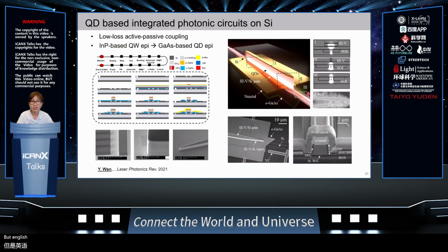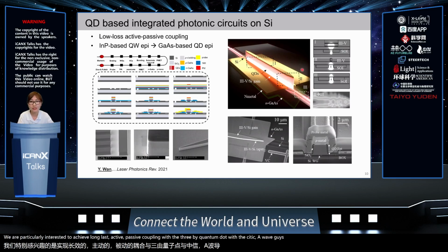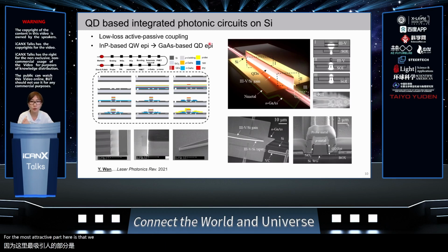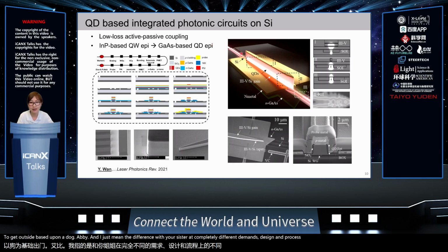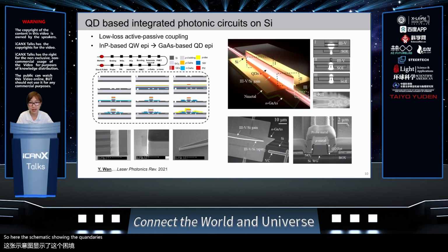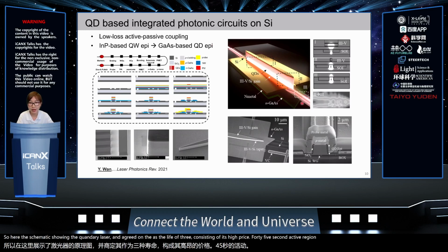But in addition to the improvement of material quality and individual quantum dot device performance, we are particularly interested in achieving low loss active-passive coupling of the III-V quantum dots with silicon waveguides to form fully integrated photonic circuits. The most challenging part here is that we need to change from indium phosphide-based quantum well epi to gallium arsenide-based quantum dot epi, and thus we need different material systems and completely different device design and process optimization. Here is a schematic showing the quantum dot laser integrated on the SOI substrate, consisting of a hybrid III-V silicon active region coupled to a passive silicon waveguide.